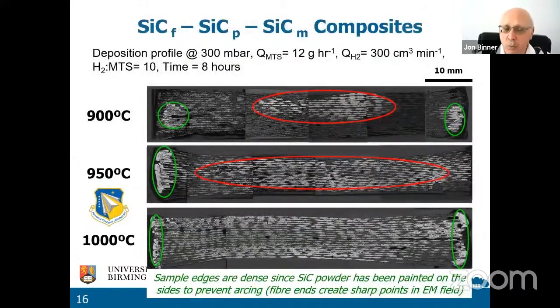And we can see the deposition profile here. So this is silicon carbide fibers with silicon carbide powder and a silicon carbide matrix. What we are doing is taking the fiber preforms, infiltrating them with powder, and now we're depositing the matrix. And you can see when we heat it at 900 degrees centigrade, we get a nice inverse temperature profile in the middle. That's the area circled in red. At 950, that profile is larger, and by 1000, we've completely cooked the entire sample.